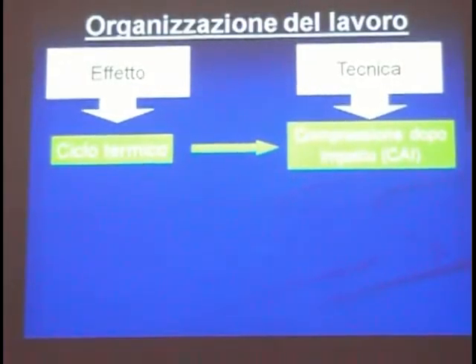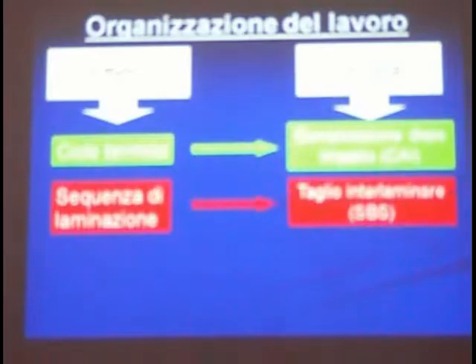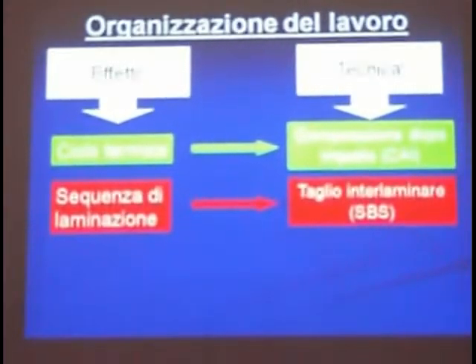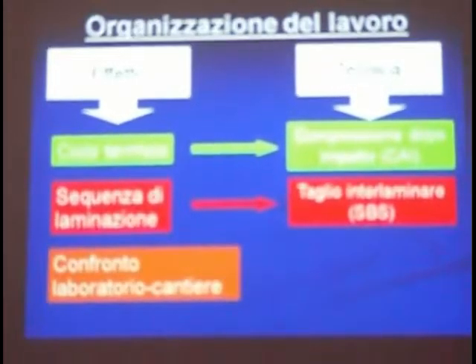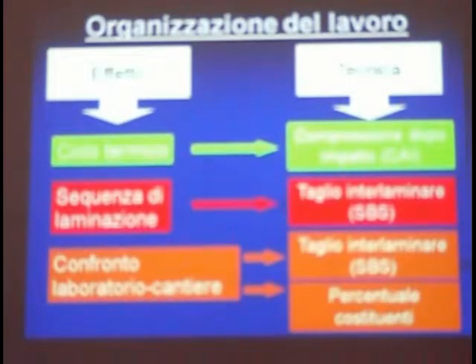So we have been studying the effect of the thermal cycle on compression after impact properties of the laminates. I will show how it works in a minute. We also studied the effect of the stacking sequence on the interlaminar fracture resistance of the material. And then we have been comparing samples obtained in the laboratory and samples taken from a boat, in order to check the properties, especially the interlaminar shear resistance and the composition of the material.